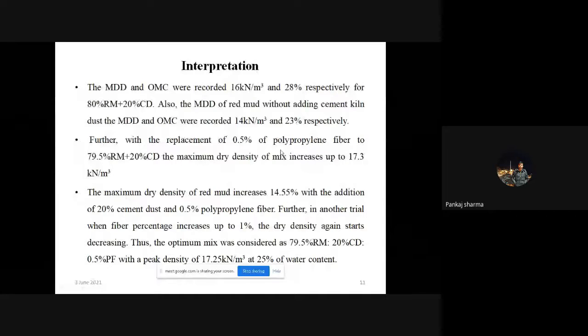The maximum dry density for the red mud without adding cement kiln dust is 14 kilonewton per meter cube and 23% of optimum moisture content. Now for the optimum mix, the maximum dry density was recorded 17.3 kilonewton per meter cube. Now further, with addition of 1% of fiber, the density decreases up to 16 kilonewton per meter cube, that I already explained. With addition of 0.5% fiber, the density increases up to 14.55% to the existing mix.